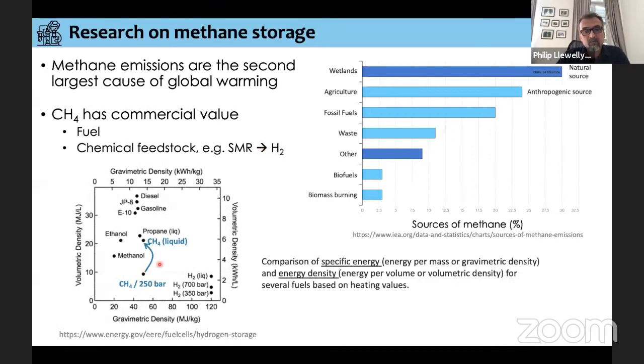The other thing, even if we do have methane under pressure, what is interesting is in terms of specific energy, so energy per gravimetric density, methane is down here under pressure, has a lower specific energy than hydrogen, and quite a similar volumetric density or energy density with respect to hydrogen. So methane could be used as an energy vector to give us hydrogen. That could be one way forward.